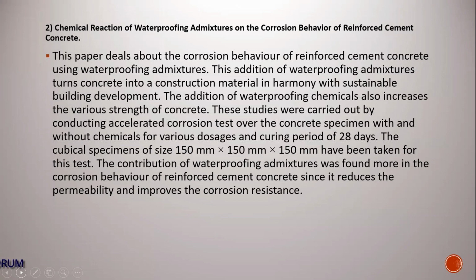These studies were carried out by conducting an accelerated corrosion test over the concrete specimens with and without chemicals for various dosages and a curing period of 28 days. Cubical specimens of size 150 mm by 150 mm by 150 mm have been taken for this test. The addition of waterproofing admixtures was found effective in the corrosion behavior of reinforced cement concrete since it reduces the permeability and improves the corrosion resistance.